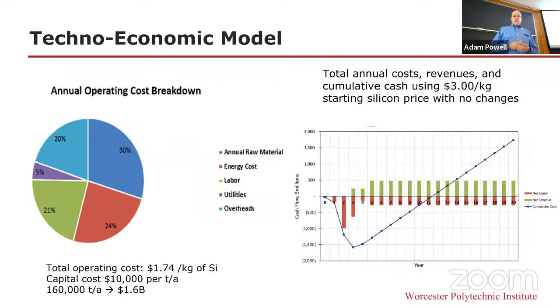A techno-economic model shows $1.74 per kilogram operating cost. This is considerably lower operating costs and capital costs, but nonetheless a very high cost for a plant. So a big barrier to entry, but significantly lower than the lowest cost today of about $8 to $10 per kilogram. As I said, with very little prospect for getting it lower because of the fundamentals of energy costs.